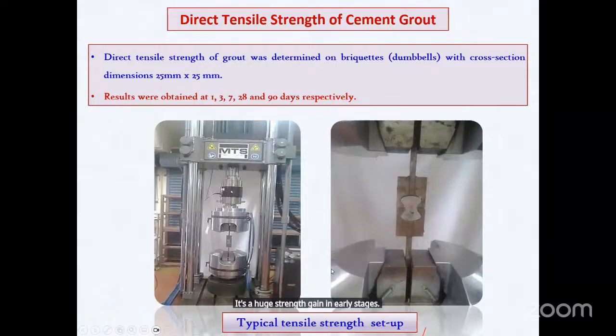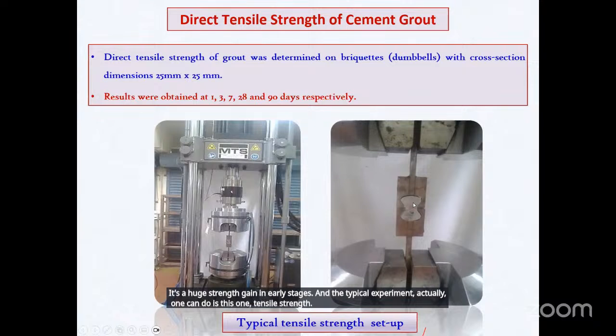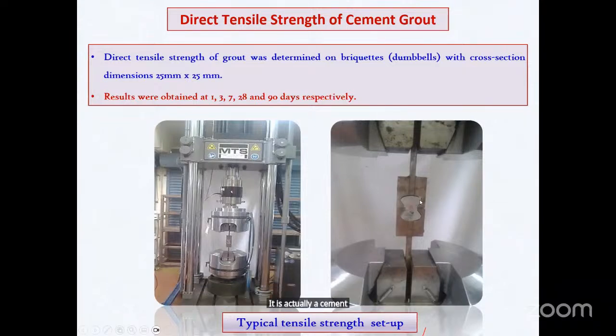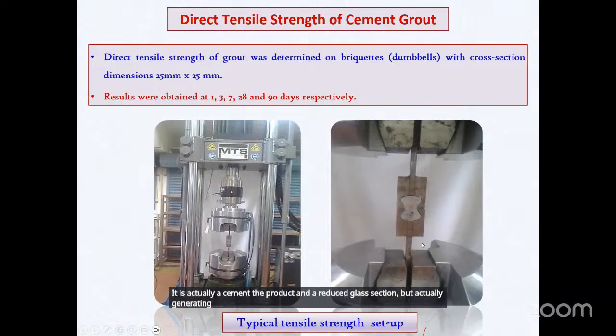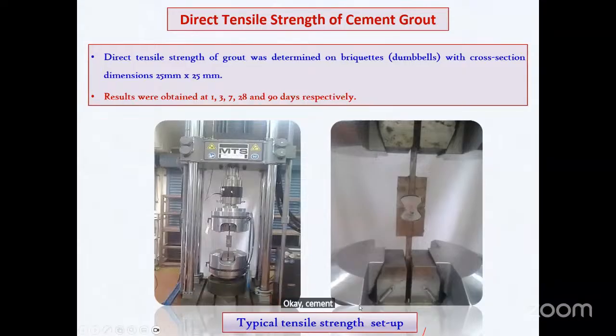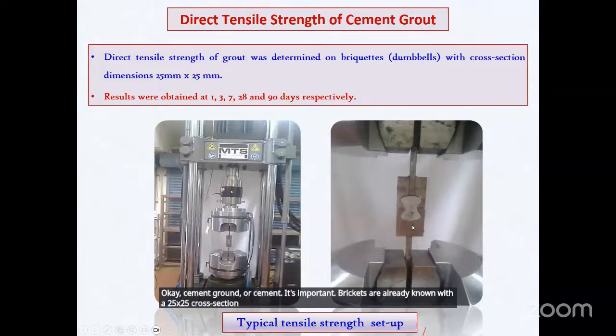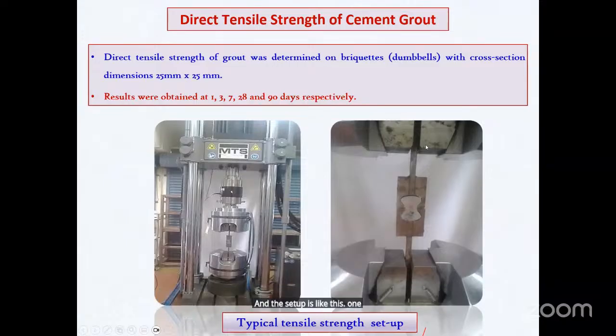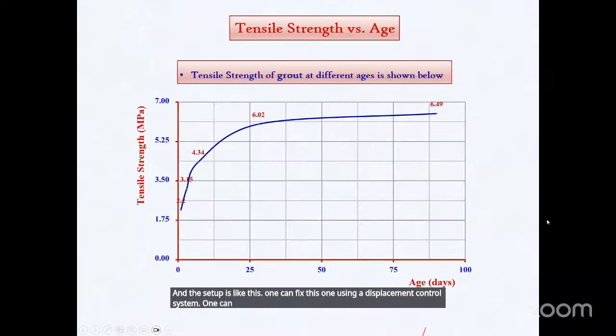The typical experiment one can do is the tensile strength. It is a cementitious product with a reduced cross section, but it generates data for understanding the direct tensile strength of cement grout or cement. It's important. Briquettes are already known with a 25 by 25 cross section. It's a reduced cross section, and the setup is like this. One can fix this using a displacement control system. One can know the strength in the early days.